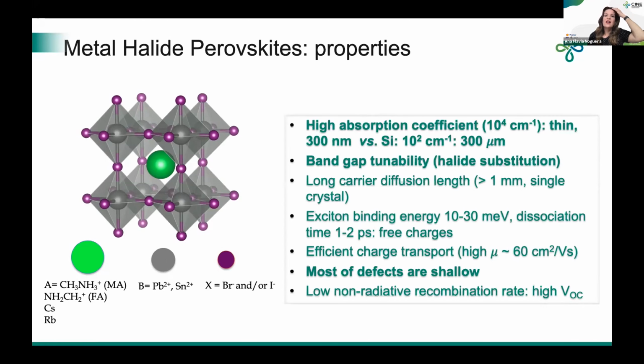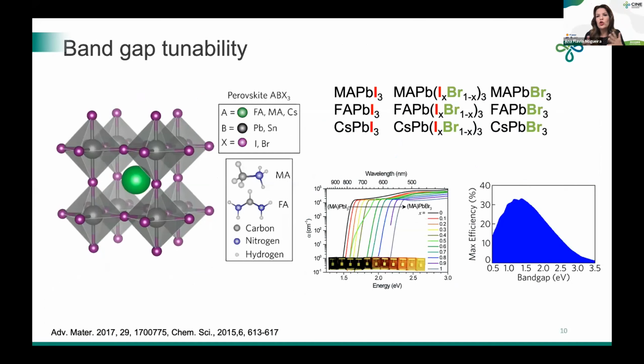So these perovskites have many interesting properties, just to cite some of them. For instance, a very high absorption coefficient. You can tune the band gap because you can play with the composition, and most of defects are shallow. Just to exemplify, when you change, for instance, the ratio between the halides here, you can achieve a very broad range in terms of absorption, from UV to almost infrared. So this is very interesting.